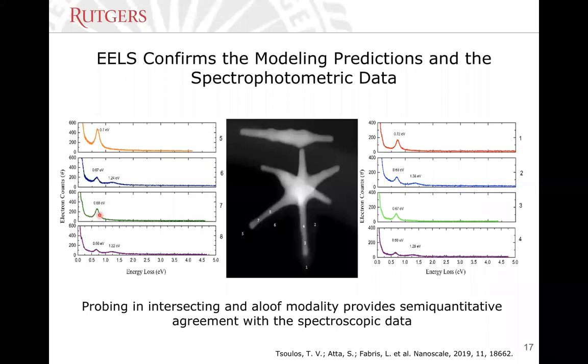What is interesting is that in these two positions, position 7 and position 5, we see only the first harmonic mode. And what is interesting about that is that our model had predicted that in position 5, the overwhelming resonant mode would be the first harmonic. You remember the red halos there. And in position 7, we would have a node in the resonant mode, and so we should not expect to see the second resonance in this position. So going forward, we would like to really extend these studies not only to the bare nanoparticles, but also perhaps coated with other materials, coated with metal oxides, coated with polymers, and see how these interactions at the interface play a role in these studies.